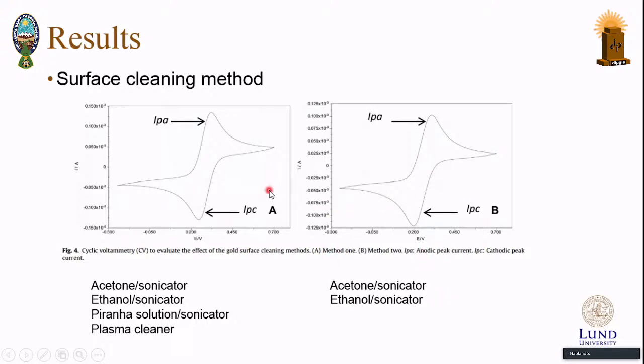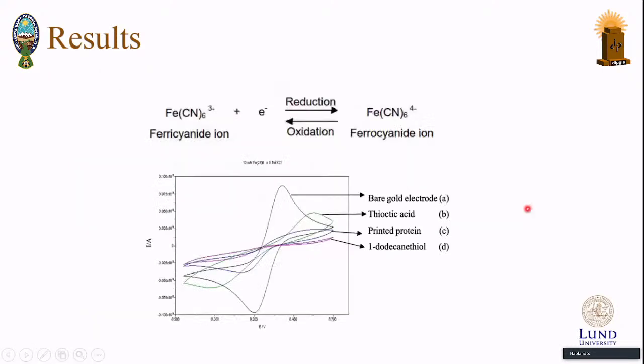And this has been confirmed by cyclic voltammetry using a reversible redox couple of ferrocyanide, where we have the anodic peak current, where the oxidation occurs, and the cathodic peak current. We can see that the difference between A and B is not so significant, so we opted to use the second method for cleaning the electrode surface.